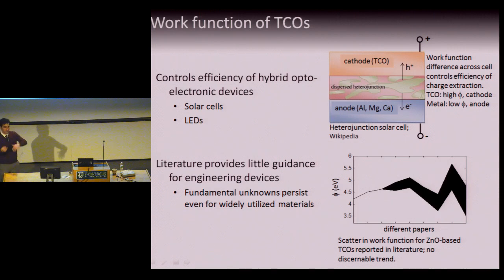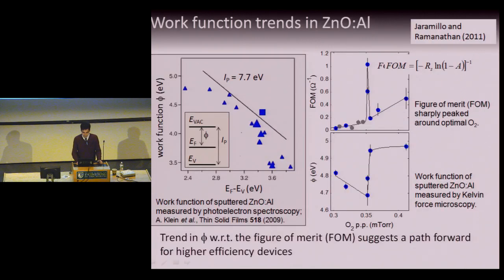So this gives you an idea of the range of work function that is reported for this narrowly defined class of materials. And it varies from peaks at over 5.5, which is absurdly high, to 3.5, which is absurdly low. This is 2 electron volts. And for anyone who's actually trying to build a device, you might as well not even pretend to know what the work function is. So my project became one of trying to measure and then understand how the work function in these materials varies as you change the growth conditions.